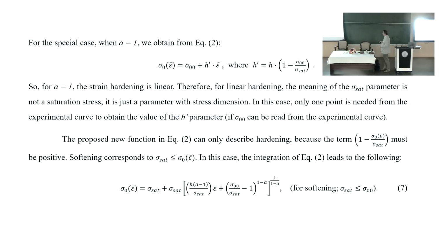But if we make it negative, in that case the saturation stress is going to be actually higher than sigma 0, or lower than sigma 0, and this becomes positive. So we get a very similar function for describing softening. This has not yet been tried, so those people who work on high temperature strain hardening could try that. I hope it works just as well.